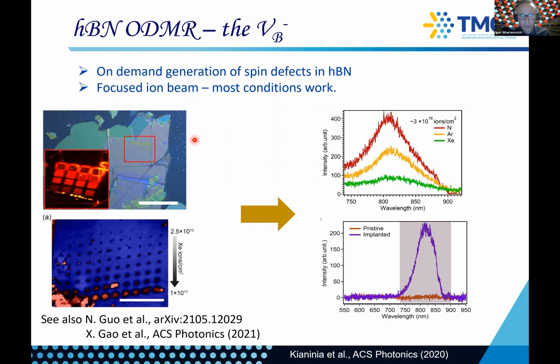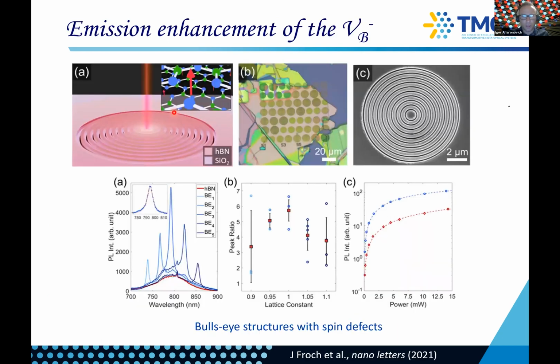So to try and address this single thing, we can then go back to our cavity fab, and we can engineer these bullseye structures. We chose bullseye structures simply because they're easy to make, and they give you a factor of 10 enhancement or so straight away. And so this is our pristine hBN here in the red, with a boron vacancy that we can create deterministically right in the middle, just by implanting any ion with a focused ion beam.